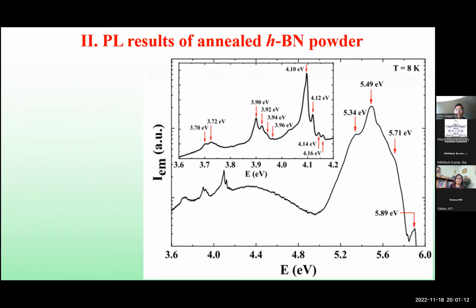So we also did a similar experiment for the boron nitride powder. And in the powder sample, we saw similar results. Peak positions are not very sharp, but the nature is the same. And we also saw a similar sharp emission at 4.1 eV. The peak position is slightly different. And additionally, it also has a few more peaks above that 4.1 and its phonon replicas.